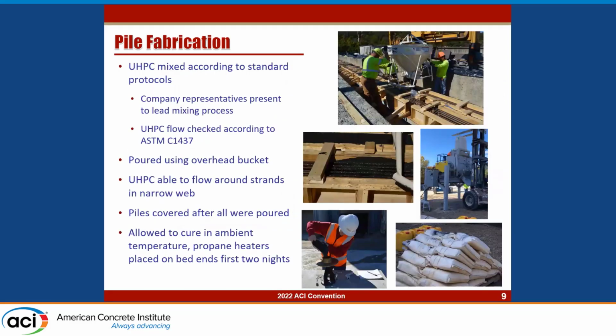On pour day, the UHPC was mixed according to standard protocols. We checked the flow according to ASTM C1437. With the high flow rate of UHPC, the normal slump test isn't quite appropriate, so the flow table is used instead. We poured using an overhead bucket, as we can see in this top photo here. And we saw that the UHPC was able to flow through the webs around the strands, even when the webs were as narrow as 2.5 inches with that 0.6-inch strand in the center. So not a lot of room in there, but it worked out for us.